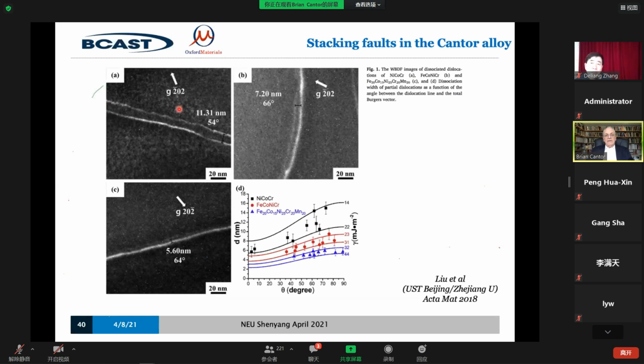But the dislocations have a low stacking fault energy, which is why the twins form. Again, just the same as copper and gold. So the dislocations separate into partials, and the partial separation varies along its length for just the same reason. The local structure is different here to what it is here. So you get different separations. Same here, you can see.